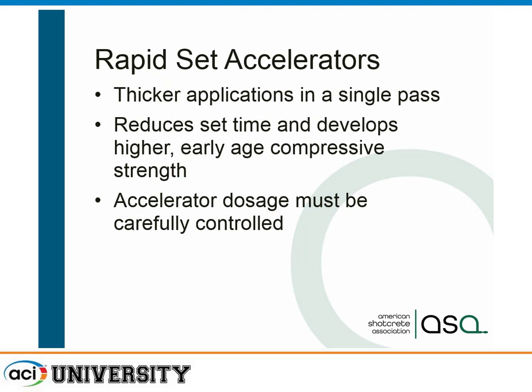Rapid set accelerators are really heavily used underground. That's not a repair application, obviously, but where they need to get in and stabilize an excavation so that they can get on to the next. But it's also used quite a bit. I mentioned that lighthouse that had the instance where they needed to get it in place, set and strength early. It may happen on a bridge deck, underside of a bridge deck. You can only have part of that open at night, or maybe you've got to put traffic on the bridge very quickly afterward. You can use a rapid set accelerator, get it to set very quickly, and also you will get strength. You can get 1,000 psi, 2,000 psi in a matter of hours.